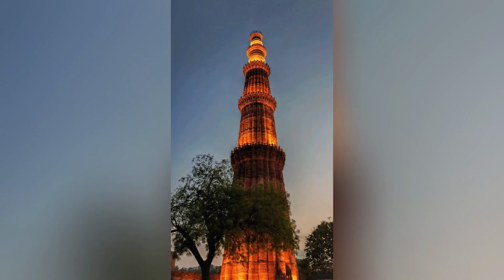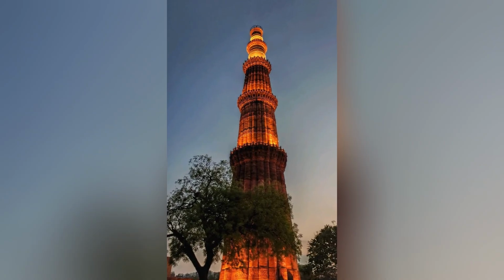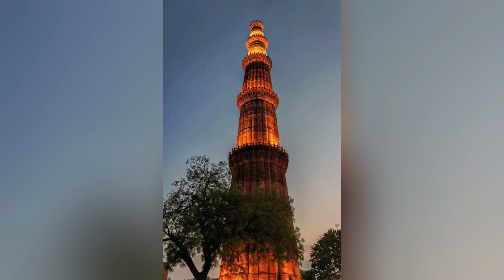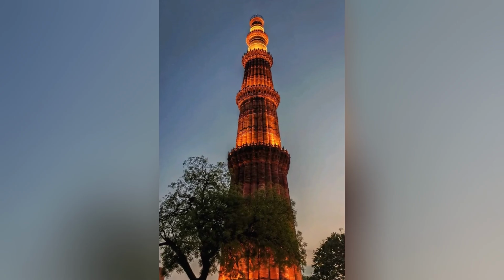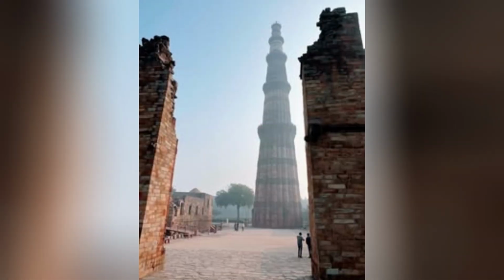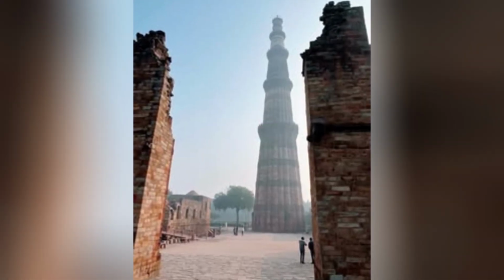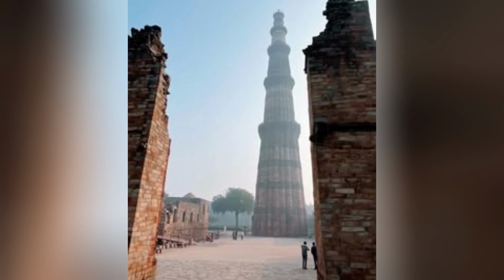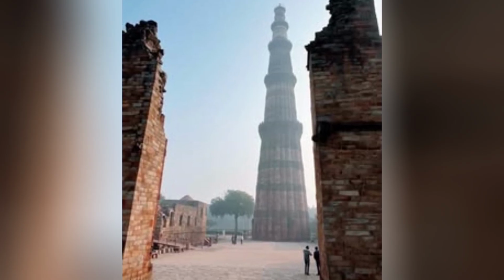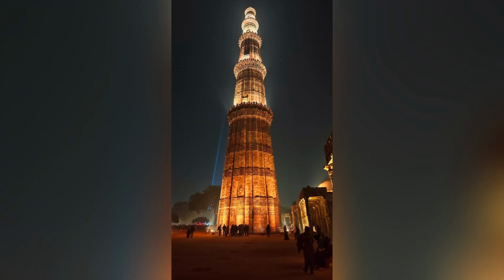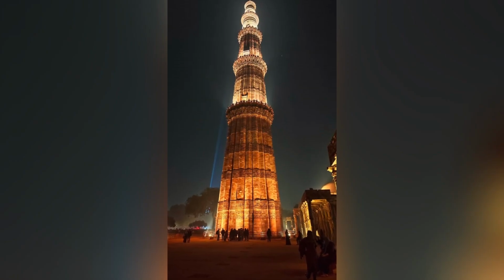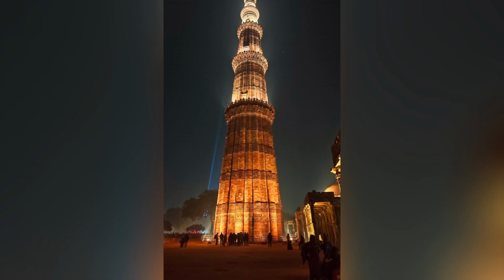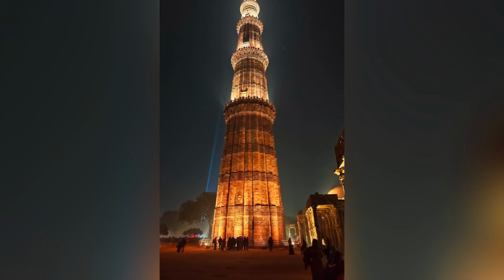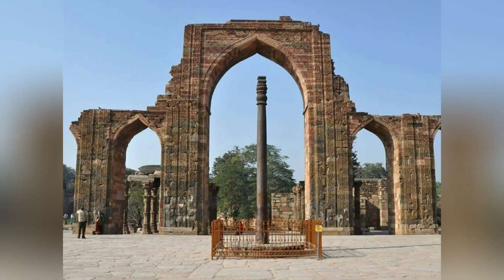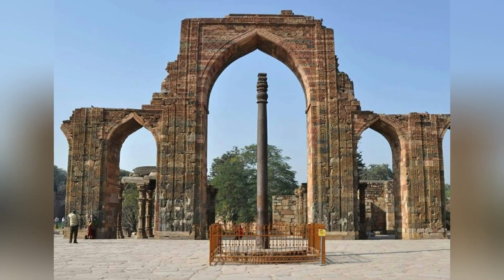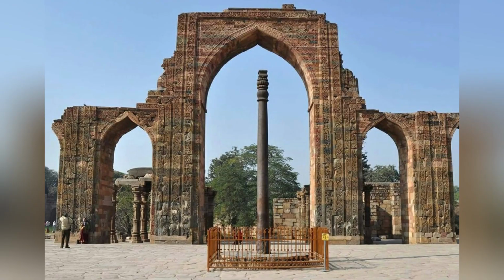The second major track of investigation has been the study of the protective film itself, aimed at understanding its composition, its structure, and the mechanism by which it protects the iron from corrosion. Balasubramaniam's analysis of the film revealed that it has a complex, layered structure with an inner layer that is in direct contact with the iron surface and an outer layer that is in contact with the atmosphere. The inner layer is composed primarily of iron phosphate compounds, while the outer layer is composed of a mixture of iron phosphate and iron oxide compounds.